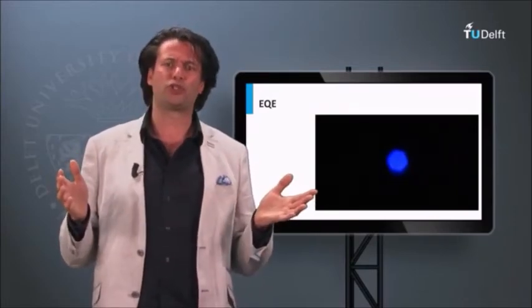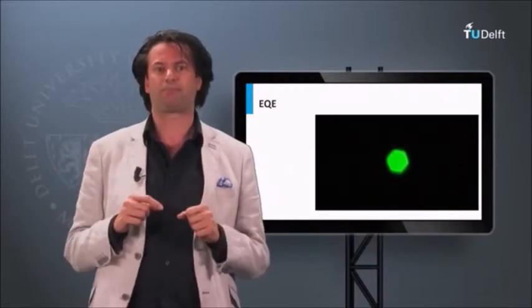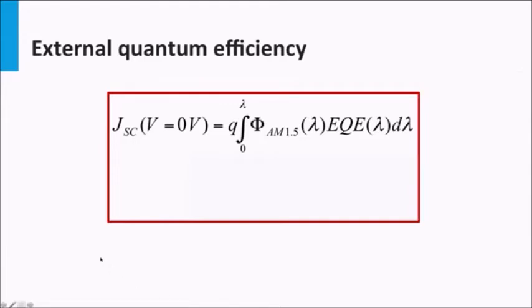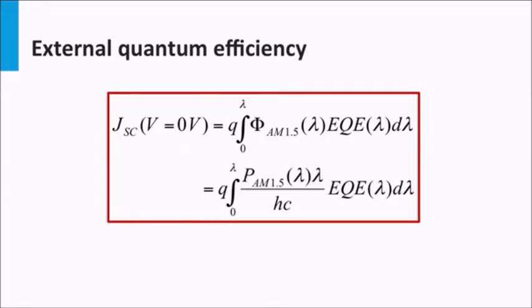How do we determine the short circuit current density out of the EQE? Under standard test conditions, the solar spectrum is defined as the AM1.5 spectrum with a total power density of 1000 watts per square meter. The total current generated at a wavelength lambda is the elementary charge multiplied by the product of the photon flux phi at AM1.5 and the EQE. The total short circuit current density can be determined if we integrate over the entire wavelength range. Or, as discussed in week 1, the spectral photon flux equals the spectral power density divided by the photon energy.